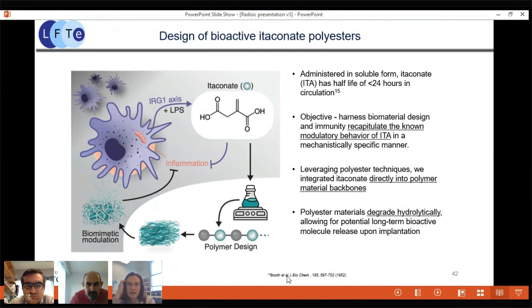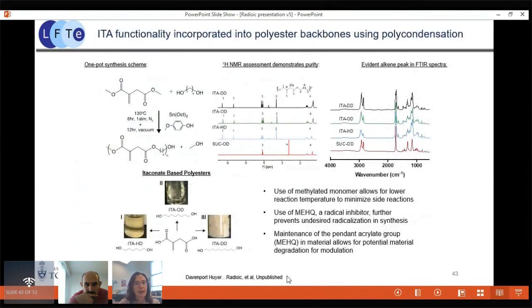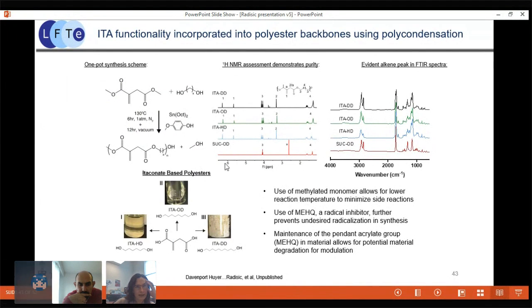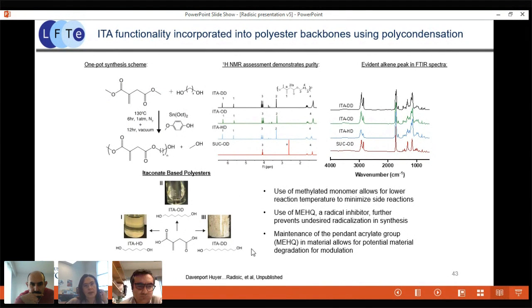The problem is when administered in soluble form, itaconic acid or itaconate have a very low half-life of less than 24 hours. And so the question is, does the biomaterial enable it to extend that delivery time and also activity of itaconic acid? And so what Locke did here is he created linear polyesters from itaconic acid and also 1,8-octanediol, as well as other alcohols.